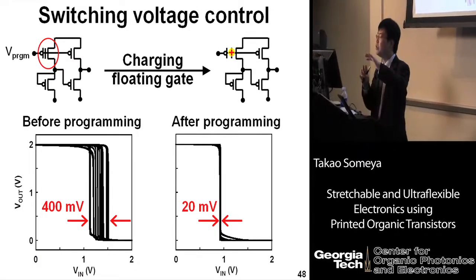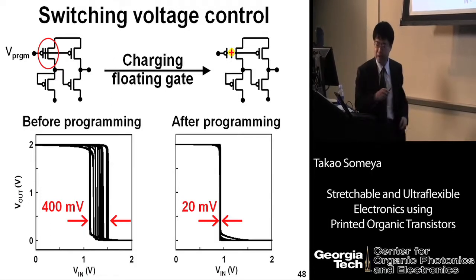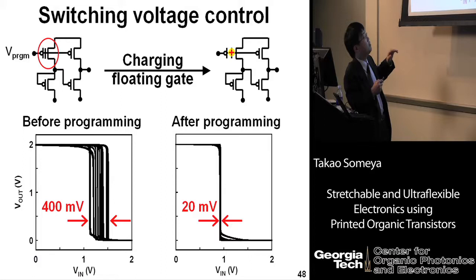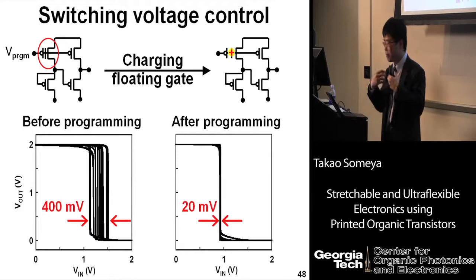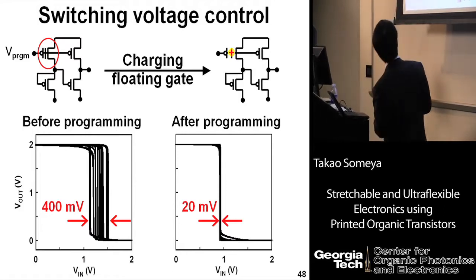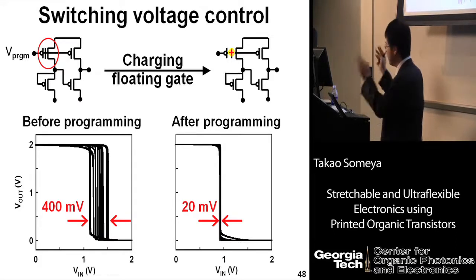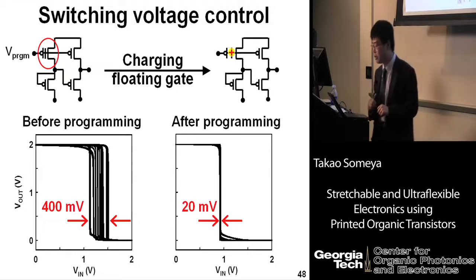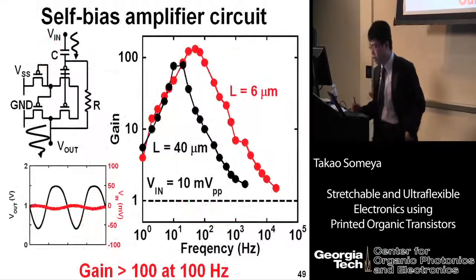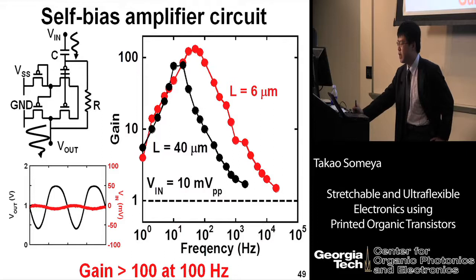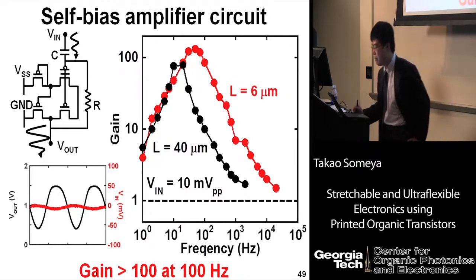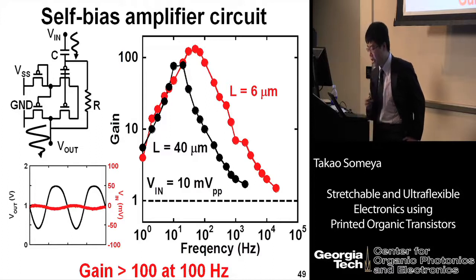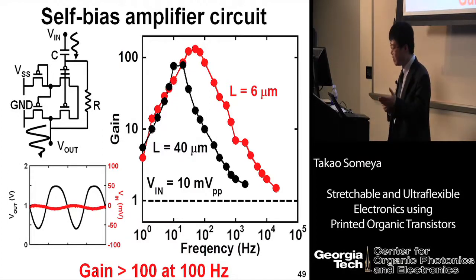Indeed, when we make the 8 by 8 amplifier, there is a fairly large performance distribution. But after programming, or accumulating charge at the floating gate structure, we can remove the performance distribution. And also, we characterized the frequency response of the organic amplifier and found the gain exceeds 100 even at a frequency of 100 Hz.